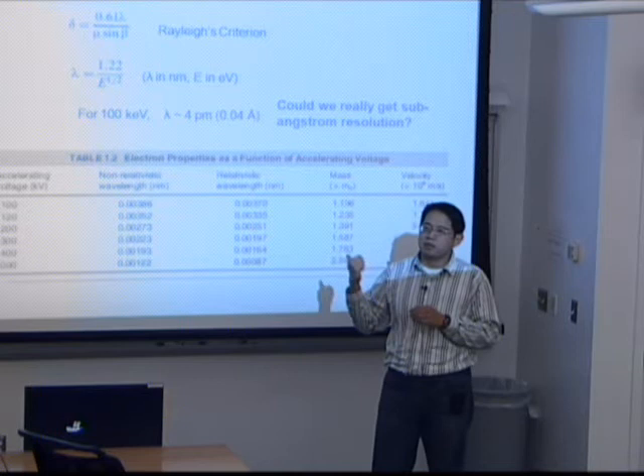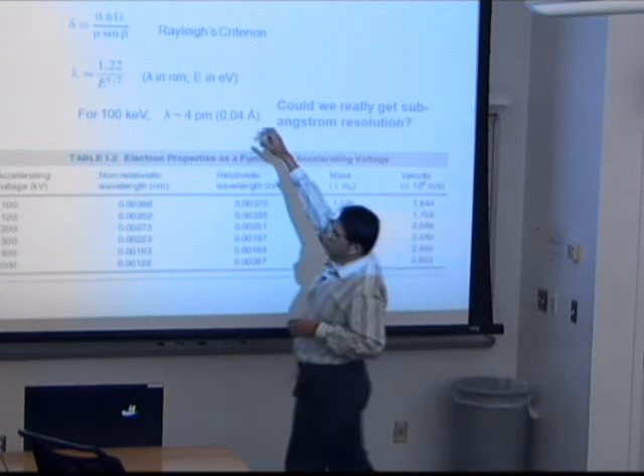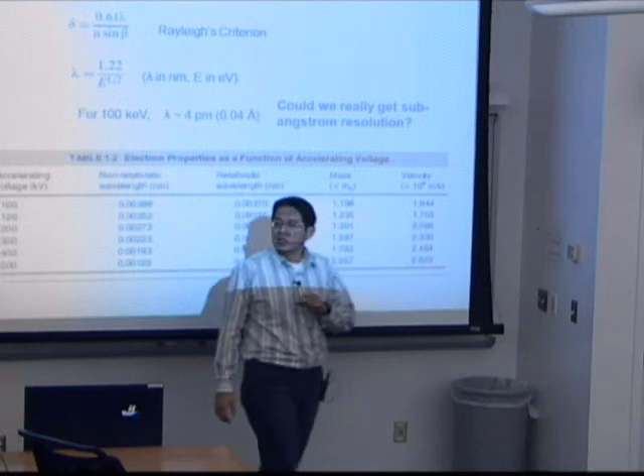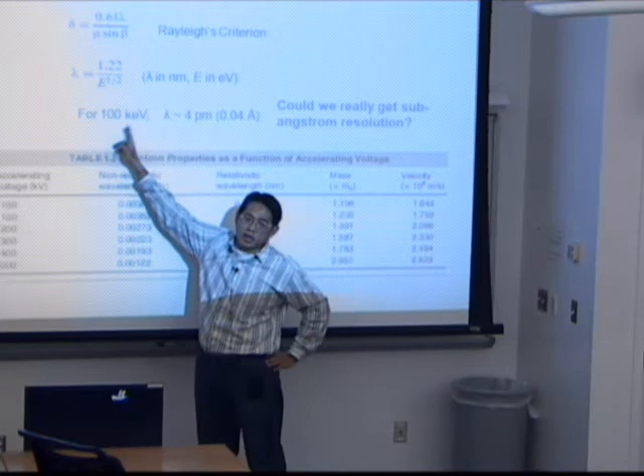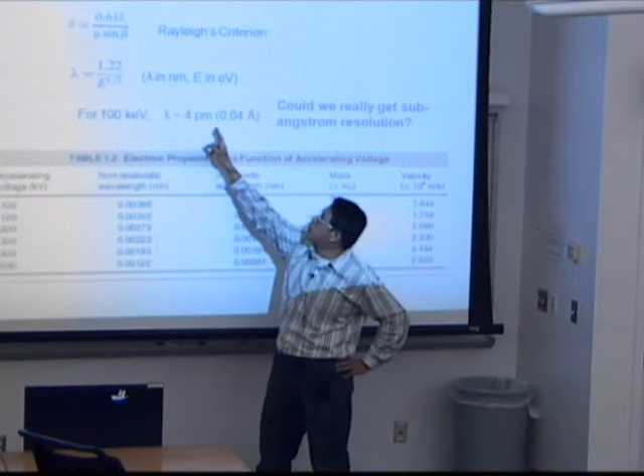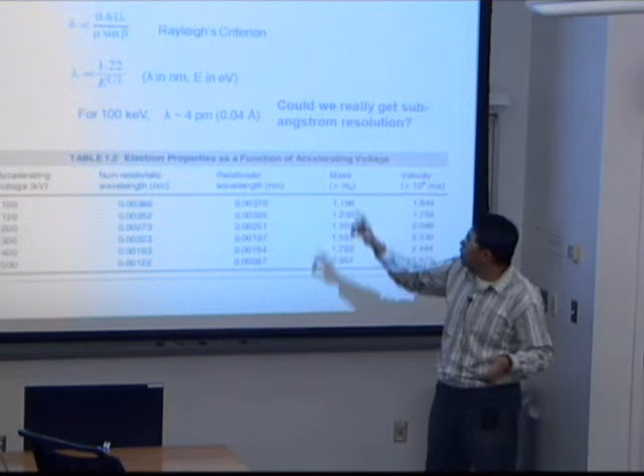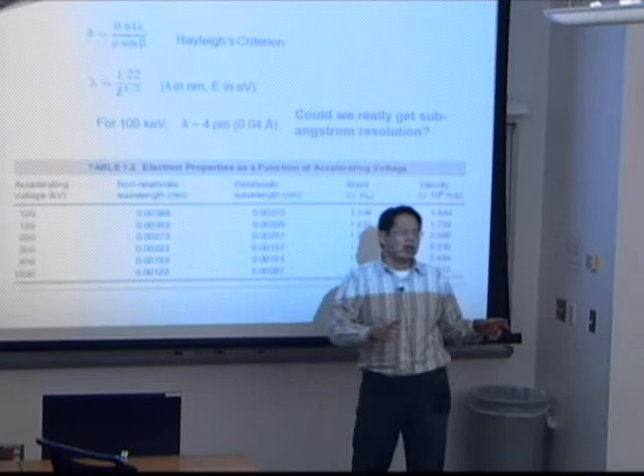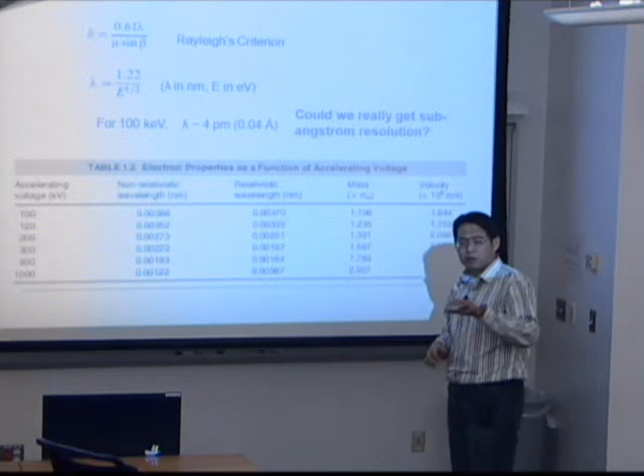For electrons, we are not using visible light — we are using electrons. The wavelength of an electron is given by the de Broglie expression; it depends inversely on the square root of the electron energy. For example, a 100 kV electron has a wavelength of 4 pm, which is 0.04 Angstrom. Since 3 Angstroms is roughly the size of an atom, the electron wavelength is about one hundredth smaller than an atom, so you could potentially have much better resolution than resolving a single atom.